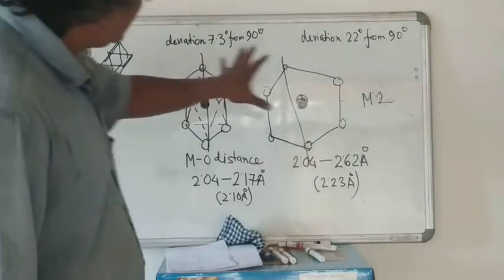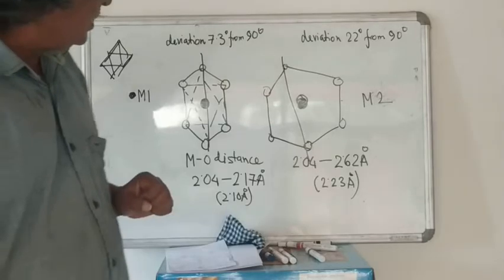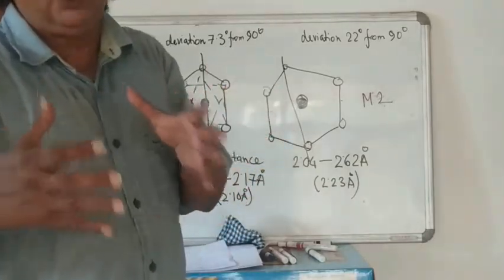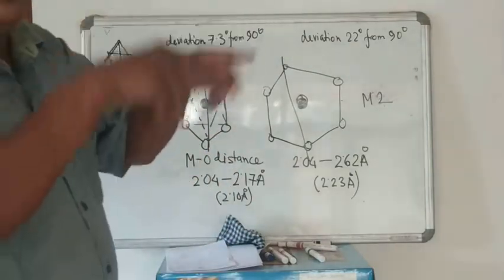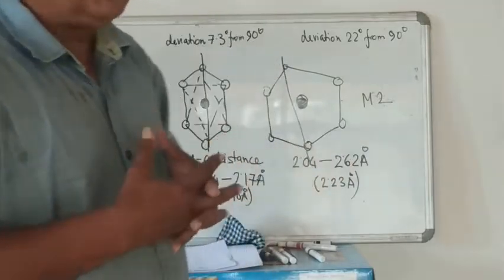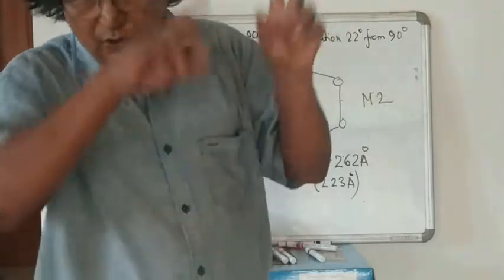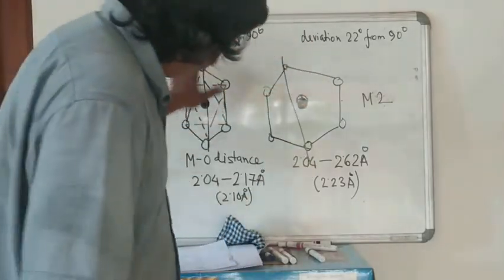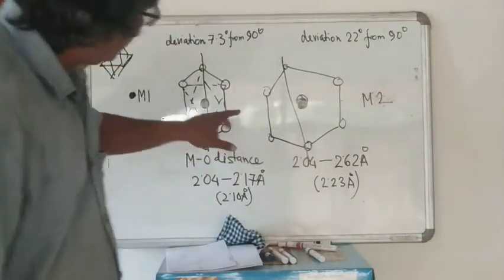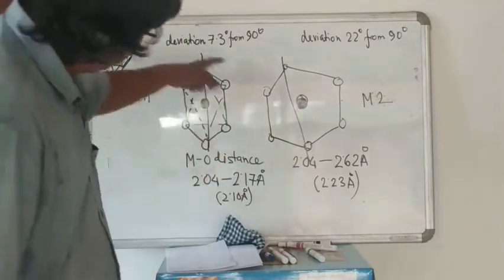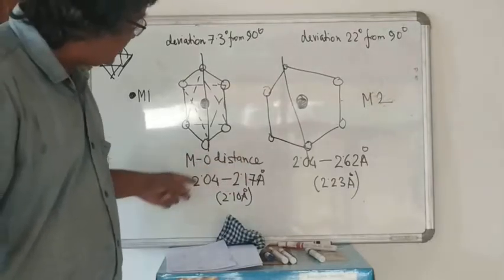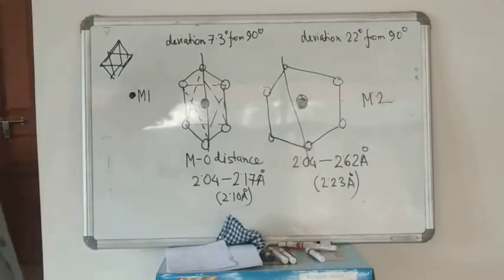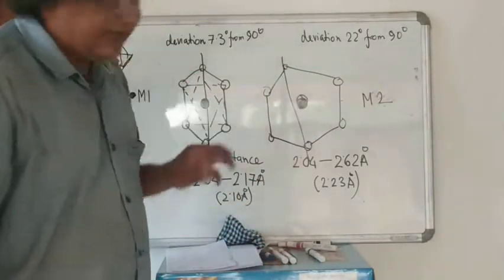Right now, we have this diagram, which was the last diagram in the last lecture, lecture 3. We were talking about orthopyroxene, or orthorhombic pyroxenes, essentially containing MgFeSiO3 and nothing else. Or (Mg,Fe)2Si2O6, which means that you have two octahedral sites, (Mg,Fe) twice, and two tetrahedral sites for silicon in the crystal structure. Both are octahedral coordination, where a single metal ion, magnesium or iron, is surrounded by six oxygen atoms, where you can see the metal-oxygen distances here have a smaller spread as opposed to this one, which is a very, very large spread. So the M2 site is a larger site and the M1 site is a smaller site.